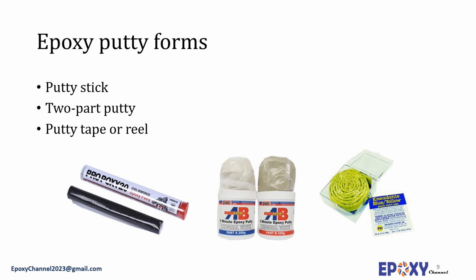Epoxy sticks are normally sold as extruded concentric cylinders with the epoxy resins and filler on the outside and polyether polymercaptan, 3-dimethylaminomethylphenol, and fillers on the inside. The epoxy putty sticks to be used need to be mixed or kneaded by hand. In the formulation of epoxy putties, it is advantageous to employ an epoxy resin with a molecular weight of greater than about 700 grams per mole. There are many epoxy resins available commercially which have molecular weight of greater than 700. However, these are solid in form and could not be used to formulate the epoxy putties without significant addition of plasticizers or diluent, which would adversely affect the physical properties of the cured product.